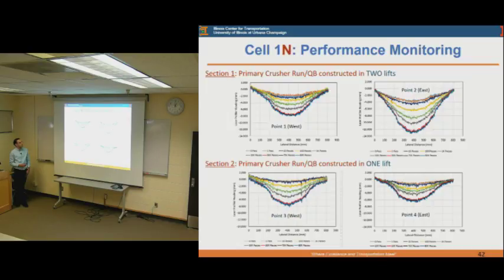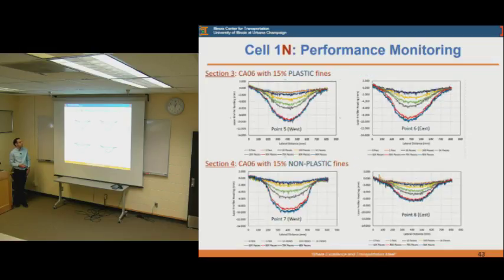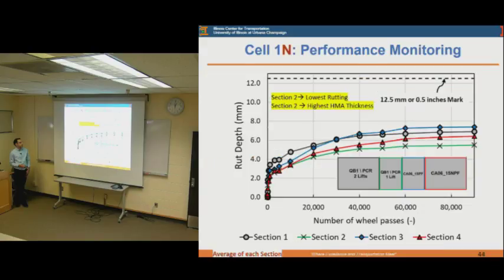Also showing the performance monitoring of the test sections and how they compare with each other. Again, there's some variability between the 2 points in each test section, but overall the rutting is much lower with the HMA paved, as expected. And just showing the summary for all the 4 test sections. So on average, the rutting in the test sections was quite similar. The rutting value that was targeted was half an inch of rutting for a low volume road as the cap.